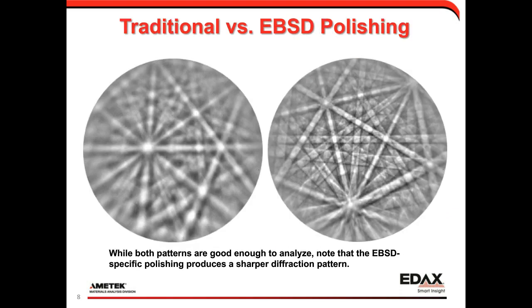And so here, if we compare the traditional polish on the left with the EBSD polishing on the right, you can see that the sharpness of the diffraction increases. We see a little bit more detail in the bands. We see some higher order bands in the pattern. And this is just due to the improvement of the polishing. And so on the very top layer of material where the EBSD patterns are formed, we have less residual deformation, and our diffraction conditions are just more strongly met, and we get better diffraction.